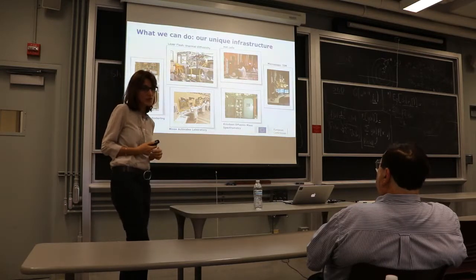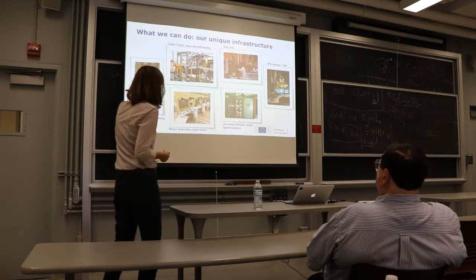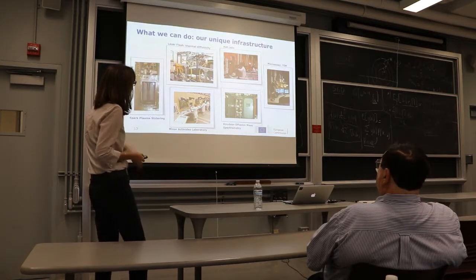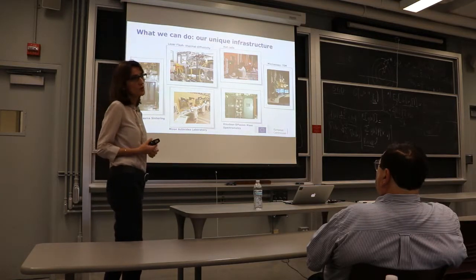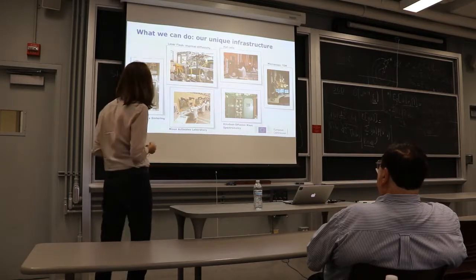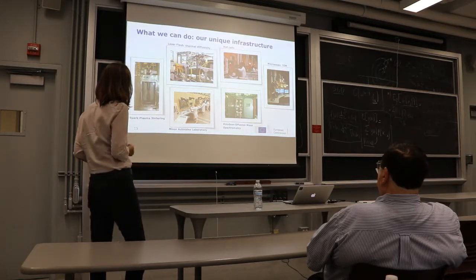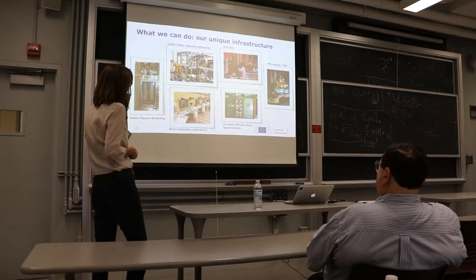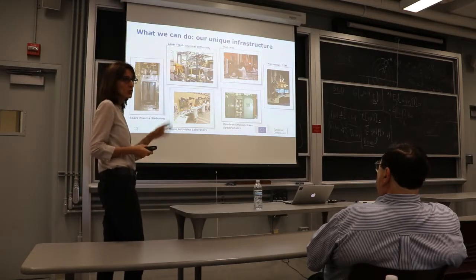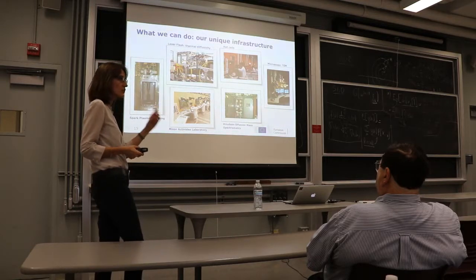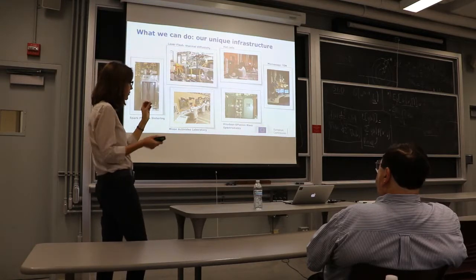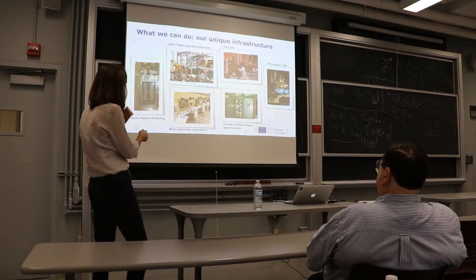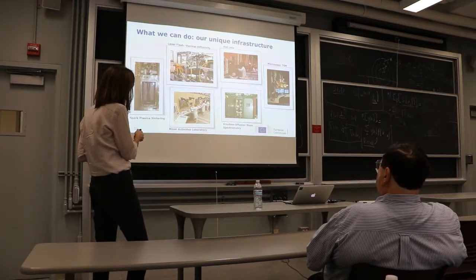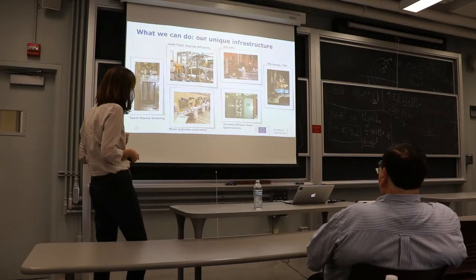A couple of pictures of our infrastructure, just to show you what type of infrastructure we have in order to work on nuclear fuel. For the synthesis, for instance, we can use the spark plasma sintering. This is a quite flexible tool where one can fabricate different types of fuels and tailoring also the composition of the fuel. Thermal diffusivity is done with the laser flash, and here we measure also thermal conductivity.